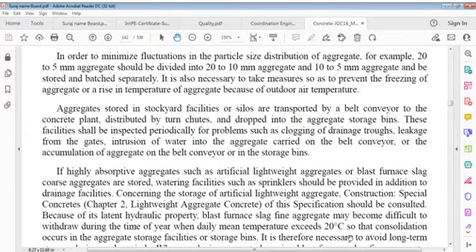5. In order to minimize fluctuations in particle size distribution of aggregate, for example, 20 to 5 mm aggregate should be divided into 20 to 10 mm aggregate and 10 to 5 mm aggregate, and be stored and batched separately. It's also necessary to take measures so as to prevent freezing of aggregate or a rise in temperature of aggregate because of outdoor air temperature.